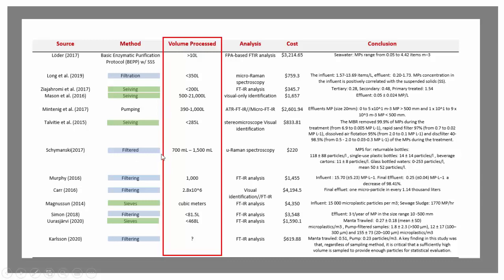And you'll see that some of these studies used as small as 700 milliliters to just over a liter. Now here's the problem. If you're using such a small sample volume and you do have natural contamination either in your sample collection or your sample preparation, or your sample preparation is so vigorous that it breaks down particles into multiple particle components, when you try to extrapolate that 1 liter to a 20 million gallon, you're going to vastly overestimate the number of particles. So there's definitely a need for large volumes for representative consistency.